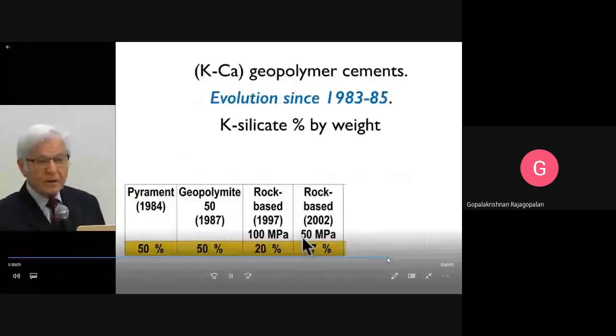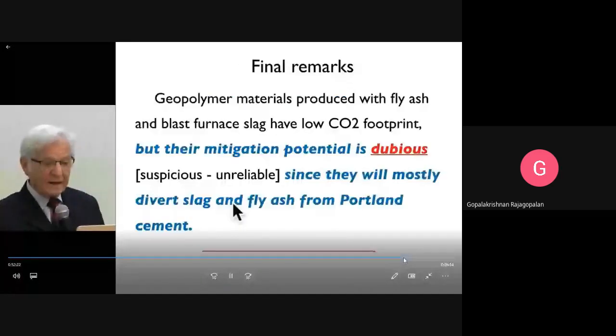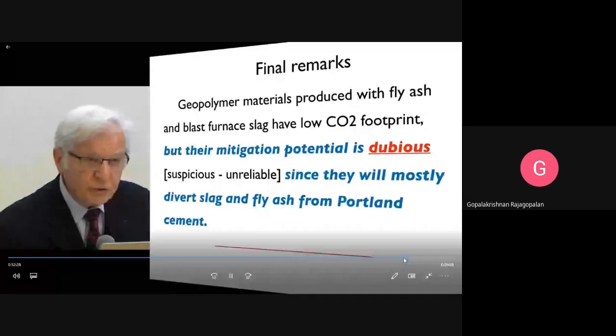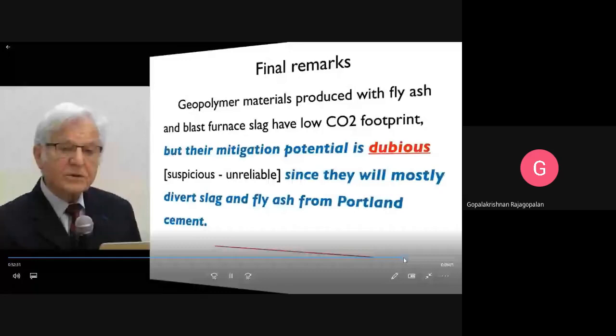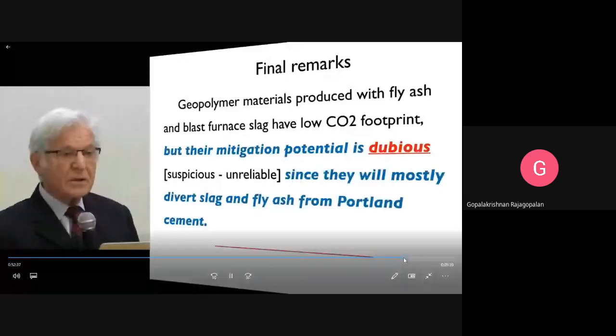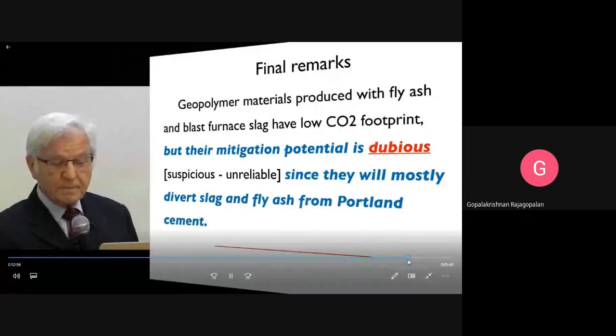So far, geopolymers that have been made by ourselves reach 50 MPa, but we had only slag and fly ash from Portland cement. In other words, in order to cut the CO2 emission by 20% for the Portland cement industry, they will use all slag or fly ash available. They want to do this provided the geopolymer cement is not developed, because the geopolymer cement can use the slag and the fly ash more efficiently, and we can cut down up to 80%. So they want to further the selling of slag.